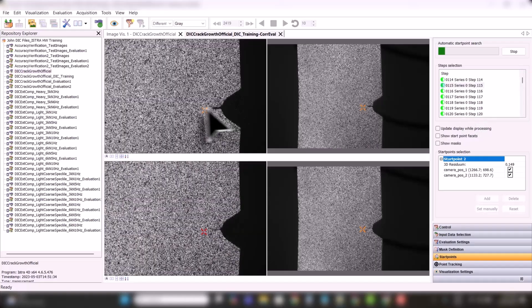Now when it comes to hugging these edges here, you might want to add even more rung steps, right? Maybe you need a lot of rung steps. And yes, that would be at the potential expense of precision, but if it goes from a precision of 0.3, 0.5 millistrain to 0.9, 1.0, that's not so bad, especially when you're just trying to fill in some of your correlation gaps of the big picture correlation.